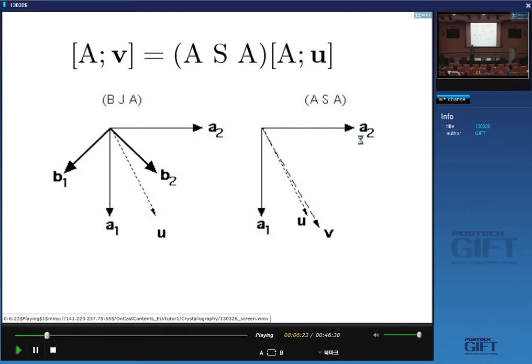Here we are going to deal with large deformations. In the Bain strain itself, the compression is very large. It's about 11% along the z-axis. You cannot use the approximations that go into strain tensors for deformation matrices.